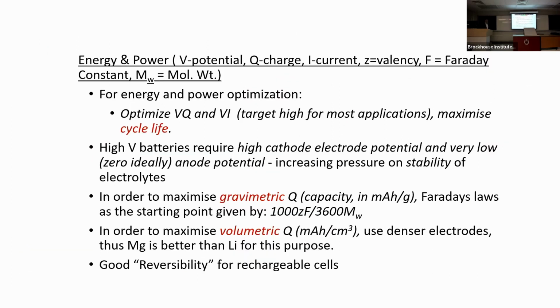Now, this is a simple calculation that one would do in order to optimize. The energy is a product of the potential voltage and the charge capacity. And for power, you multiply the same potential with the current. For most applications, the target is to be as high as possible, and you want to maximize the cycle life. Now, high voltage batteries require a high cathode electropotential and a very low, ideally zero, anode potential, so the difference is as large as possible. But as soon as you have that, the electrolytes become unstable.